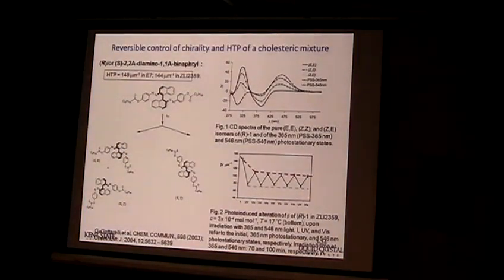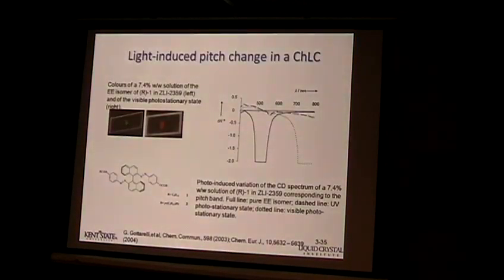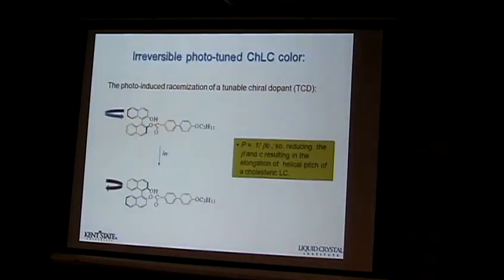Because you see, this type of material has some lifetime issue. The other thing is this image will last for a while, but once the temperature changes, the relaxation process gradually takes place, and then the image gradually disappears. So that's kind of a disadvantage. If you like full color, you will see my blue become a bluish green or the blue disappear. So you don't want that, right? So this is a reversible process.